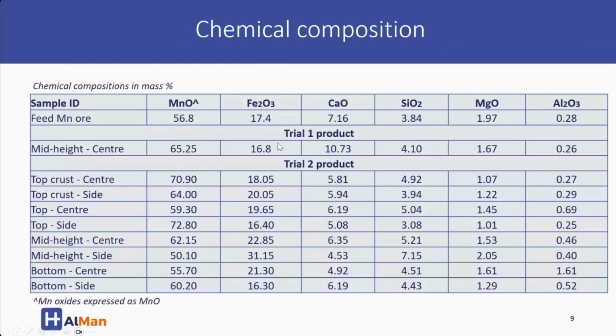So, like I said, we only did 2 tests. In the first trial, we didn't take temperatures at 3 points because the material was discharged before that could be done. So we just took representative grab samples to do a quick analysis. Also, just to mention, this manganese is expressed as manganese oxide - not actually MnO, just expressed for simplicity.